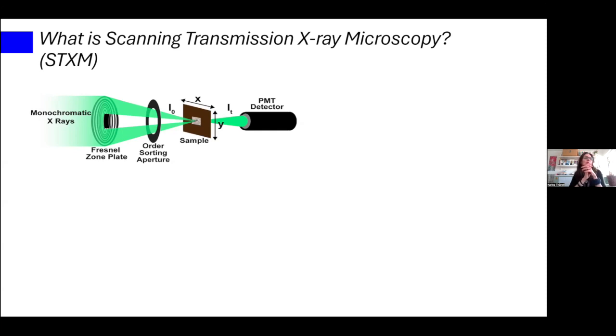You can see on the zone plate, the middle bit is also taken out, because what you typically also get is beam that is not diffracted by the Fresnel zone plate. So the middle section would be a beam that is not diffracted at all. Both that and the other orders that you don't want get blocked by the central stop on the zone plate, and then the rest by the aperture. By the time we get to the sample, what we have is a spot a couple of tens of nanometers in size, typically 20 to 60 nanometers in diameter, a round spot on the sample.